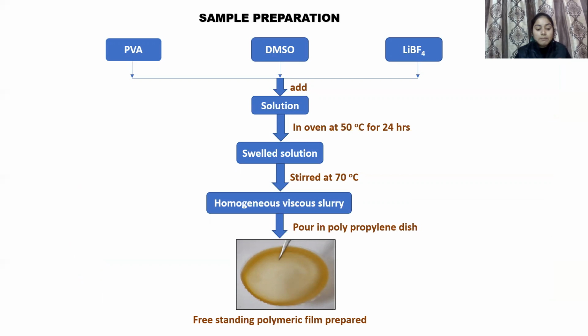PVA plus X weight percent of LiBF4 based polymer electrolyte films were prepared by using the solution cast technique. In this method, the desired amount of PVA and LiBF4 were mixed together with DMSO solvent, and then this mixture was kept in an oven at 50 degrees centigrade for 24 hours to swell. This swelled solution was stirred continuously at 70 degrees centigrade until a homogeneous viscous slurry was formed. This slurry was then poured into a polypropylene petri dish and allowed to evaporate at ambient temperature. And finally, a freestanding polymeric film was obtained.